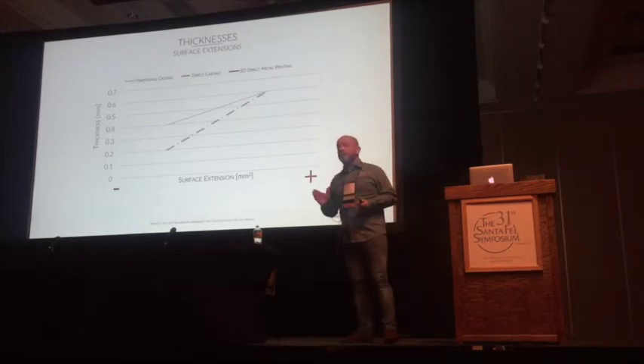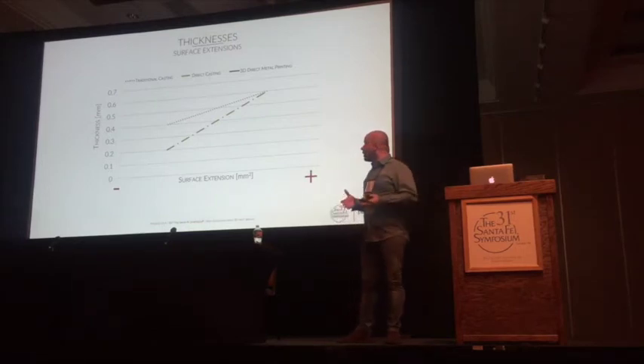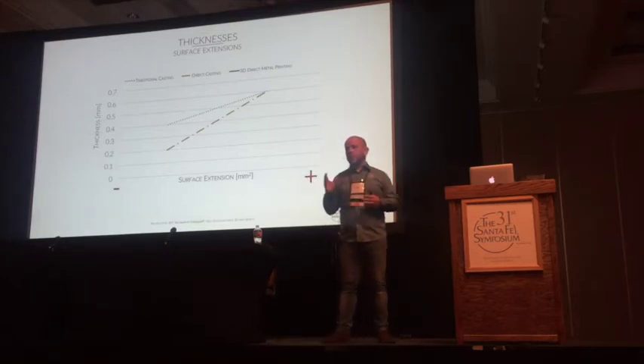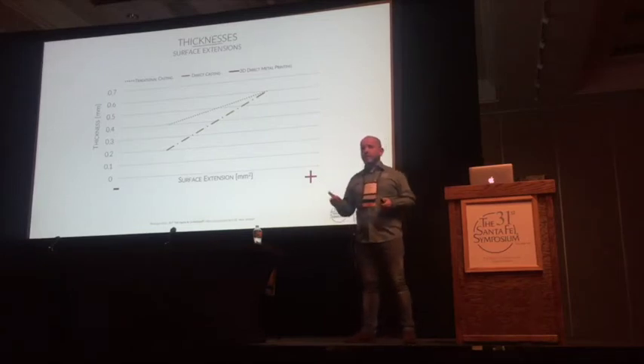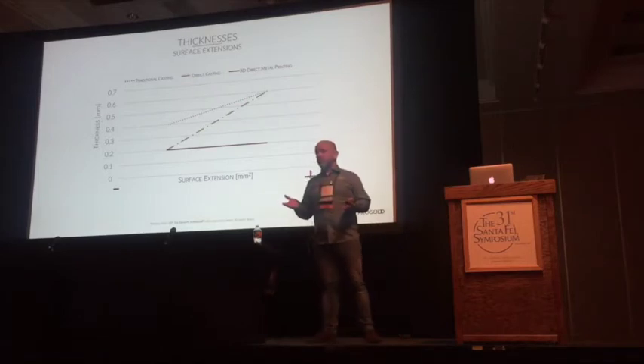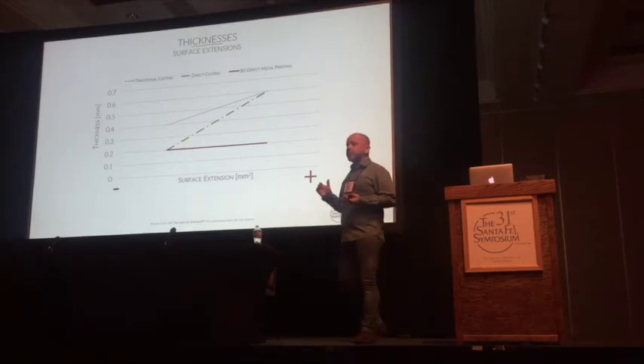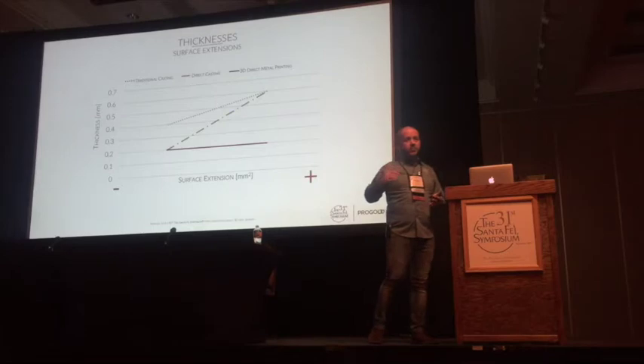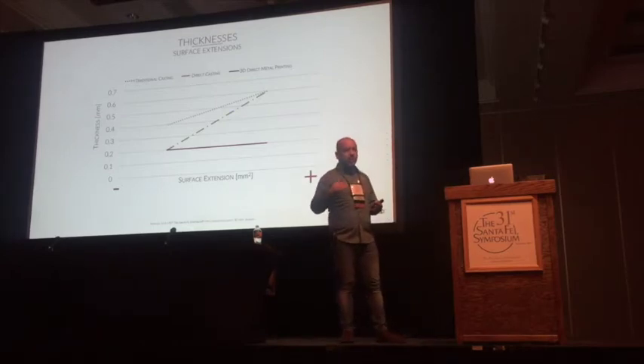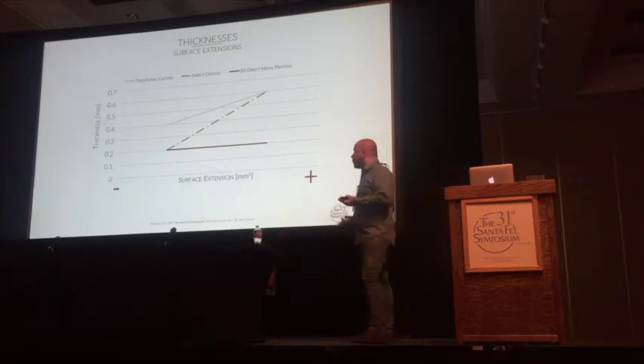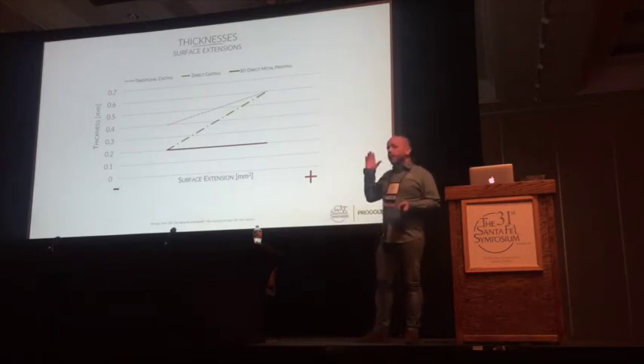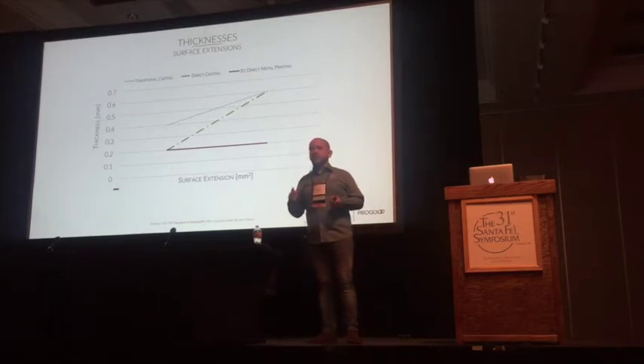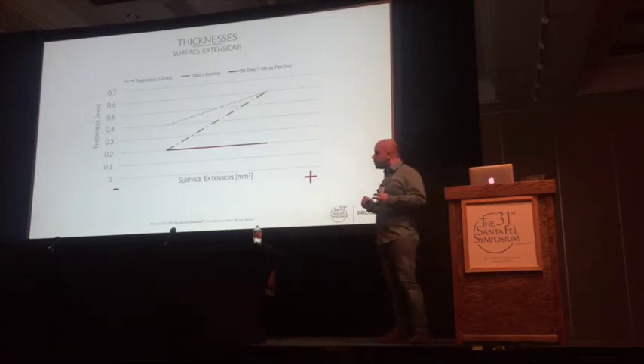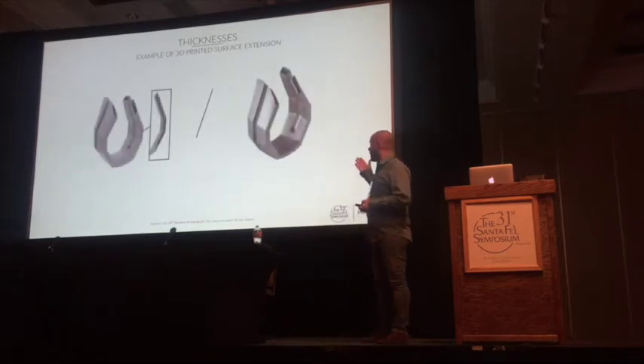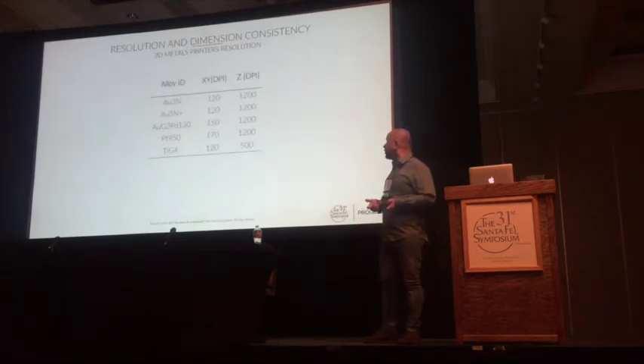Then, in the case of direct casting, no problem, because you 3D print the pattern, and then you have a very thin wall or thin details, but then you face the barrier of casting problems. In the case of 3D metal printing, there is not this problem, because you go to 0.2 millimeter, this is the standard thickness that you can print in the case of gold or titanium, but then when you go for platinum, for example, you can go down to 0.15 millimeter for whatever the surface size you are going to reproduce. So this is one of the best paths that we should walk through to take advantage of 3D metal printing. Here is an example of a titanium part with a very thin wall and very extended wall that can be easily produced by 3D metal printing.